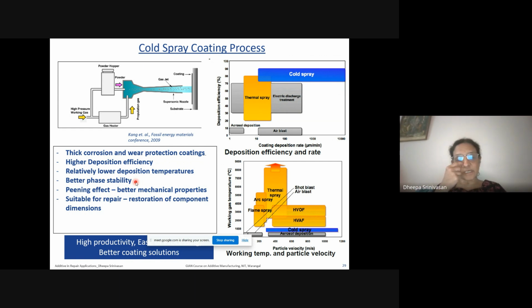And the other advantage, especially in the lot of Air Force related applications in the last 15 years, is that they're using cold spray for very difficult to weld and repair alloys, like light alloys like magnesium, titanium, which will catch fire, aero engine materials, aluminum, very very difficult to repair, cast iron, for example. So all these, cold spray is seen as a very good repair technique. Moreover, cold spray is also akin to shot peening, so that fine powder particles are coming and impinging on it. Since some of the light elements like aluminum, titanium, it even is able to give some kind of a compressive residual stress and enhances the fatigue behavior of the base metal.